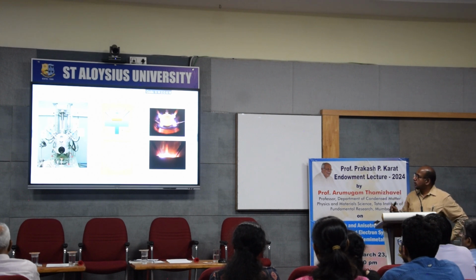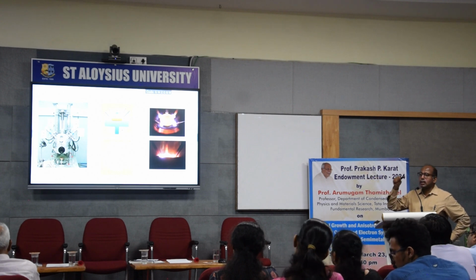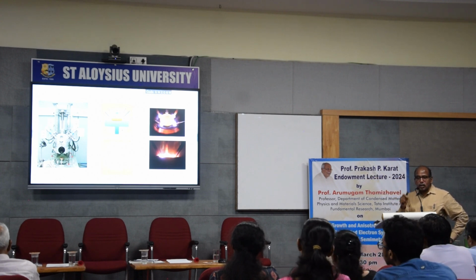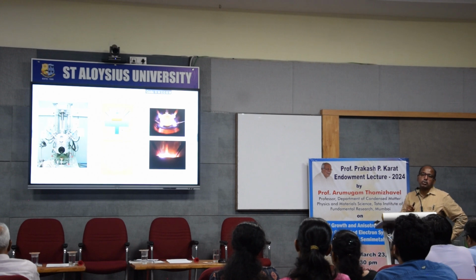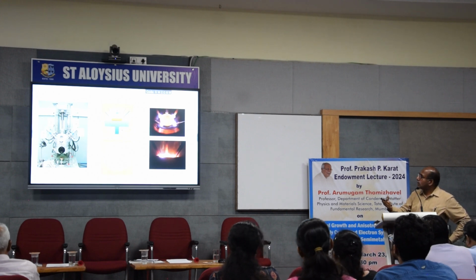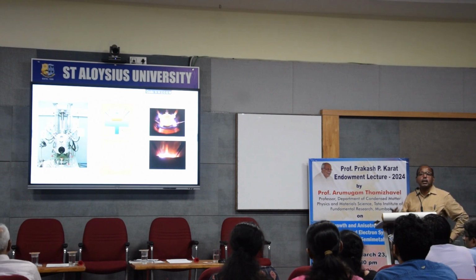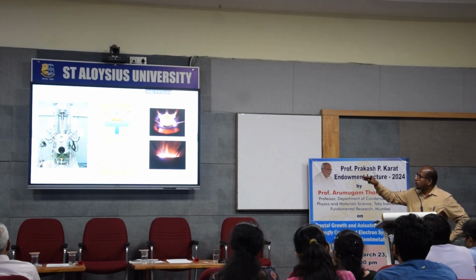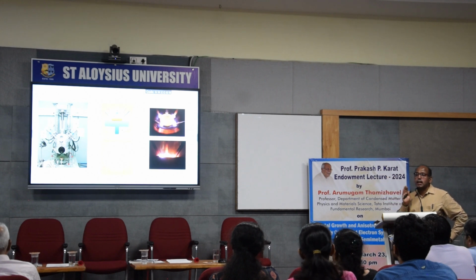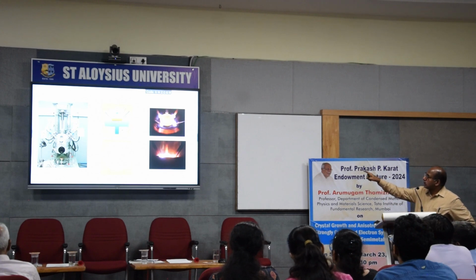The left side figure shows that there are 4 electrodes, 1, 2, 3, 4, which are nothing but thoriated tungsten rods. You pass a huge current to these tungsten rods. These tungsten rods will make an arc, and from that you can melt the samples. You can melt samples whose melting points are as high as 3000 degrees centigrade. So when I put the chamber down and I strike the arc, I can reach temperatures as high as 3000 degrees centigrade. This is the basic principle.